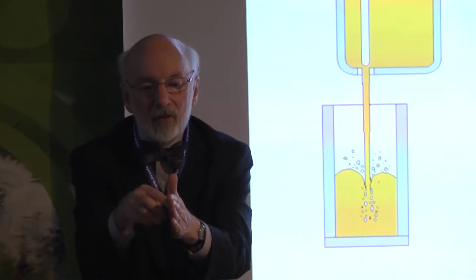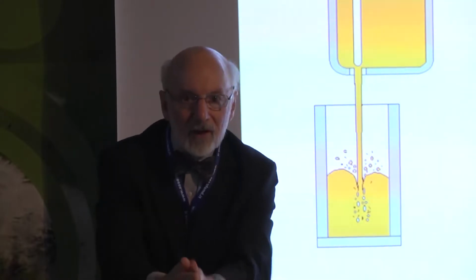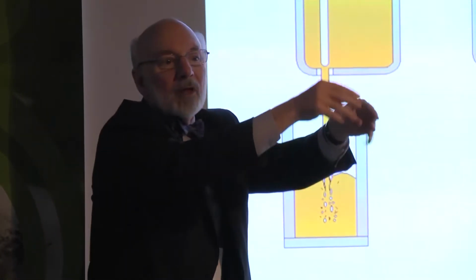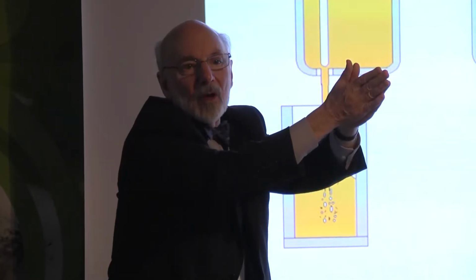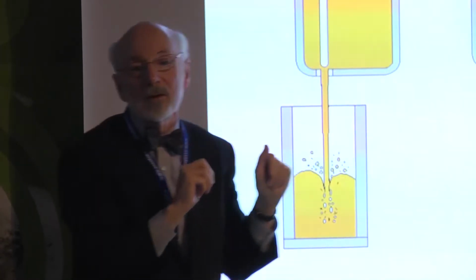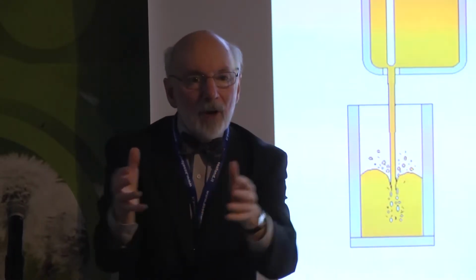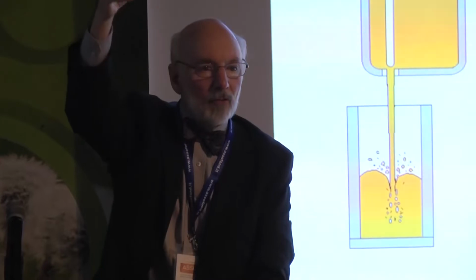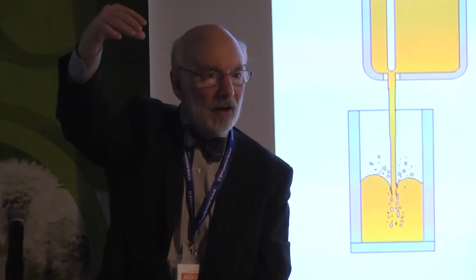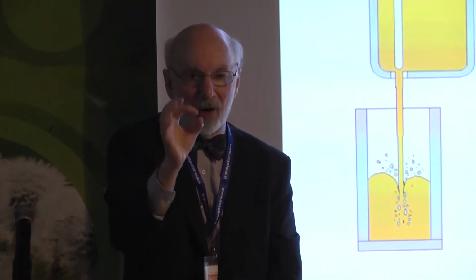It comes together, so there's no bonding now, and that goes back through the system, all the way down through the gate of the casting, along the runner, up the sprue, probably about halfway up the sprue, the point where the air was first entrained. So now we have this bubble trail, and the bubble goes up, leaves this long trail as a long crack. So now you have cracks in the casting, probably 1 meter long, from one bubble.